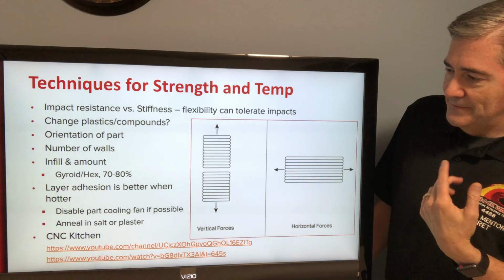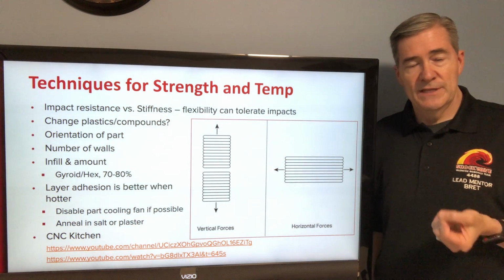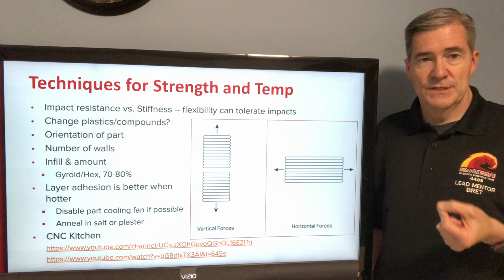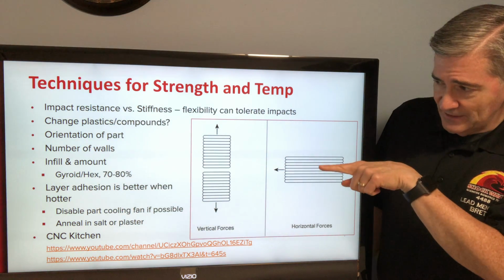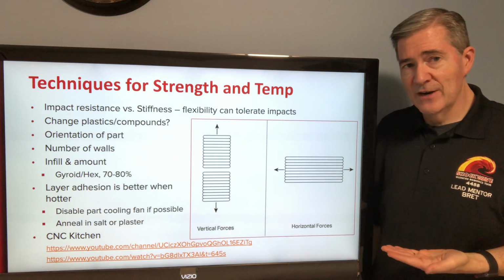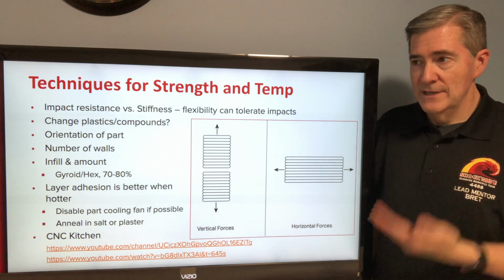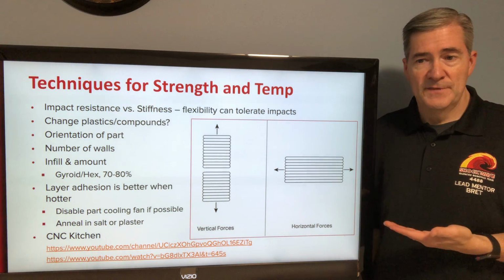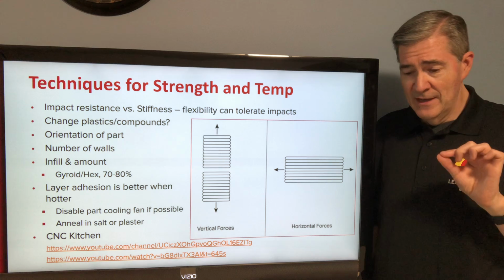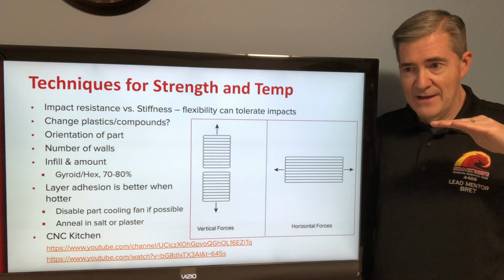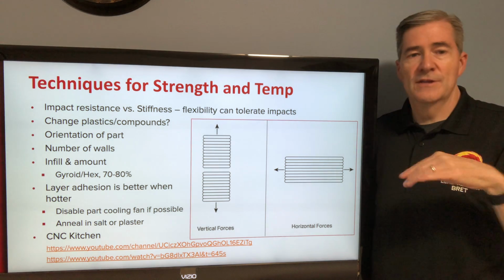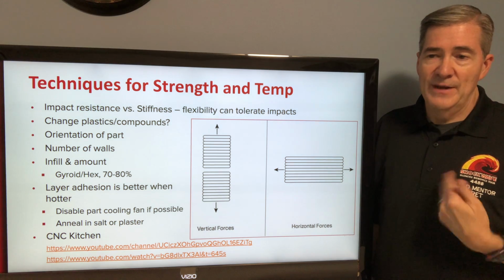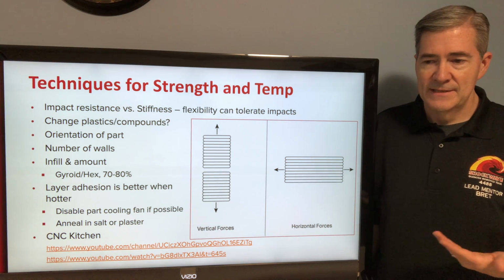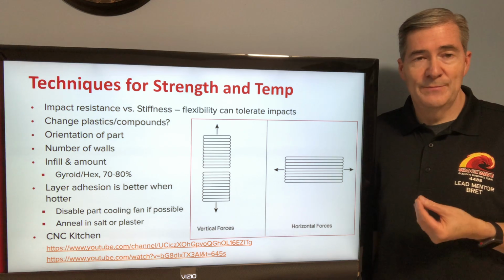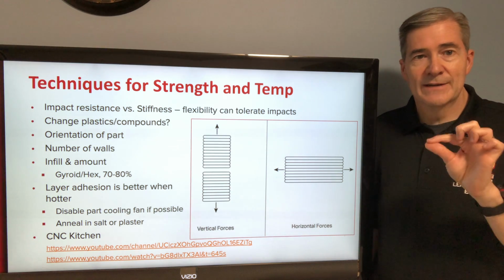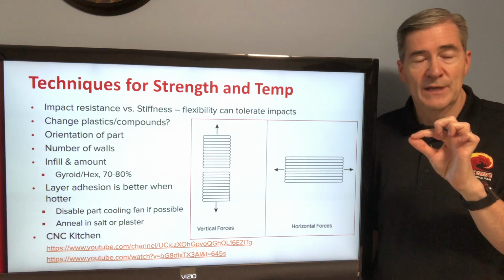And the other things you can do, if you really need to increase that layer adhesion strength, is disable the part cooling fan, and you can increase the extruder temperature. Increasing the extruder temperature means you have more problems with drooping. So if you're bridging, you'll end up with a little bit more droop. But if your part doesn't have any bridging in it, then being able to print at a higher temperature ends up giving you better layer adhesion because it melts the two layers together more.